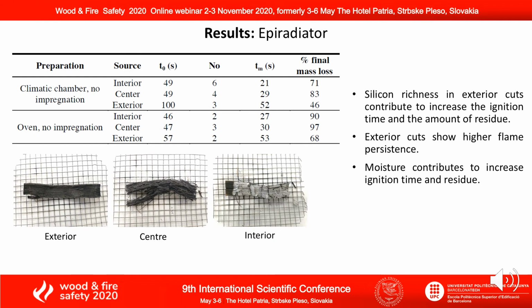However, in the Epiradiator results, we can observe that the external layers, richer in silicon, show higher ignition times and higher amounts of residues, but when the flame appears, the persistence of this flame on the sample is also higher than for the internal and central parts. And as expected, moisture contributes to increase the appearance of the first flame, so the ignition time, and also the amount of residue.